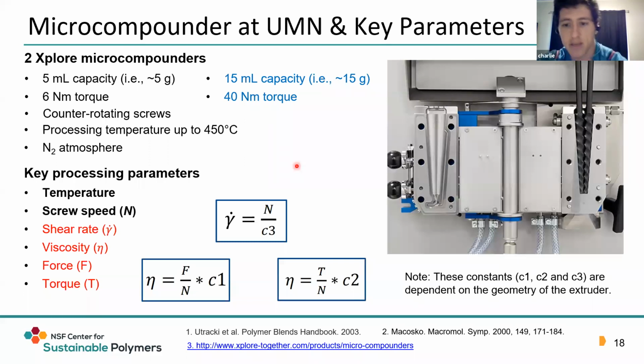Some key processing parameters that you can tune are temperature and screw speed. The screw speed can be converted to the shear rate through this equation here, and the melt viscosity can be measured through the force and torque as seen there. So again, in situ measurements can be recorded while mixing.